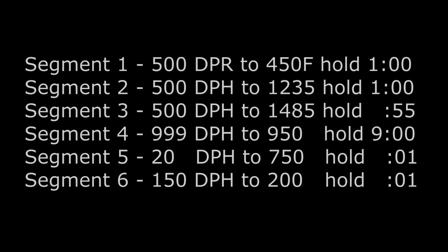I fire it at 500 degrees per hour to 450 and hold for an hour. 500 degrees per hour to 1235, hold for an hour. 500 to 1485, hold for 55. Quick down to 950, 9-hour hold. 20 degrees per hour down to 750, hold for a minute. And 150 degrees per hour down to 200 and hold for 1 minute.